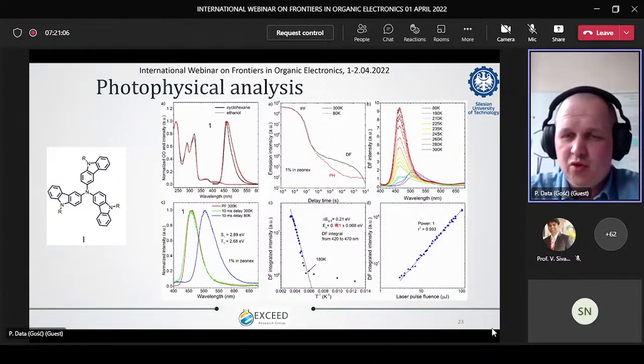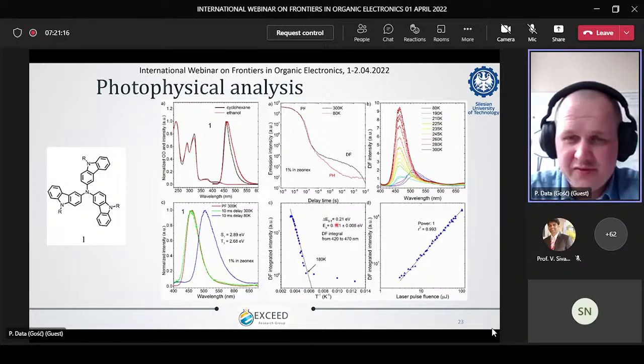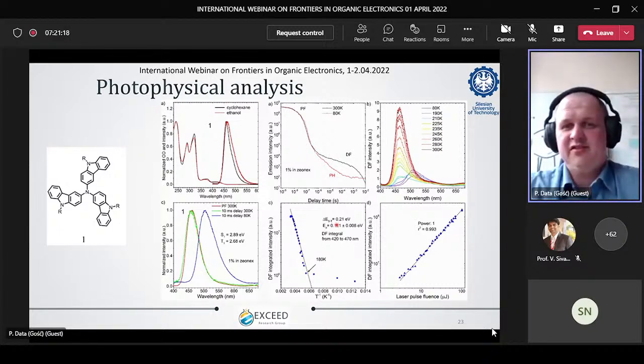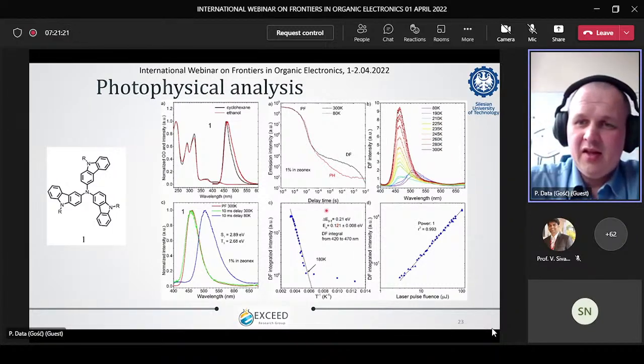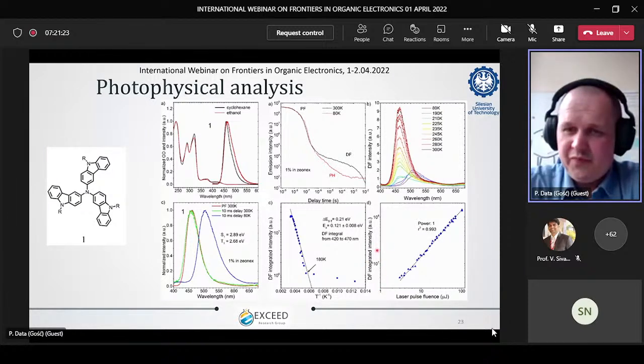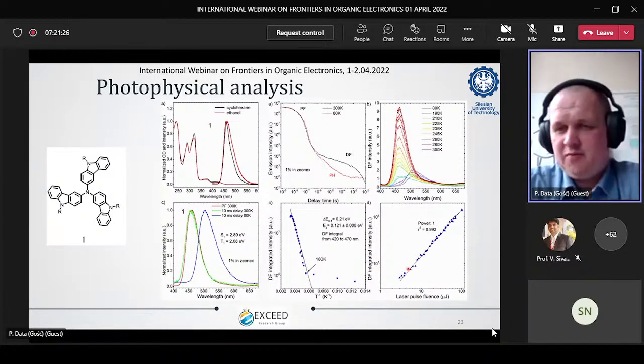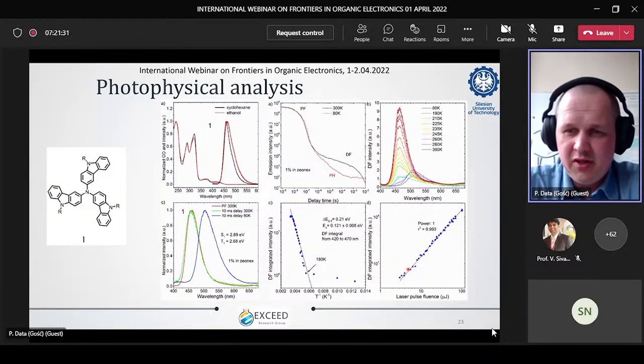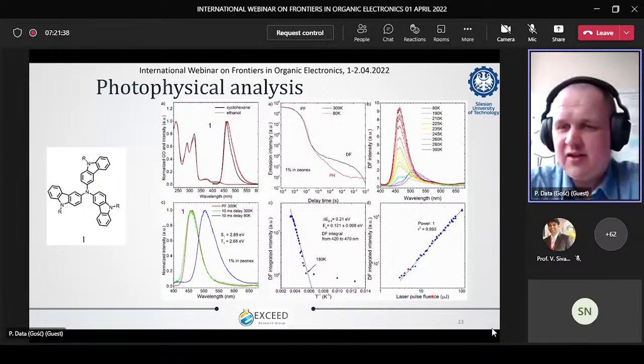Nevertheless, this is a more sophisticated analysis. For typical screening of emitters, when organic synthetic students or professors are synthesizing hundreds of them, we need to screen them much faster. And finally, to differentiate between the TADF process and the TTA process, the only way to directly prove that is, I would say, laser fluence analysis, which is again a similar process.